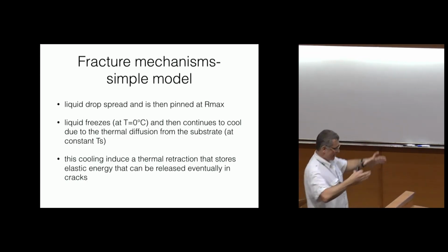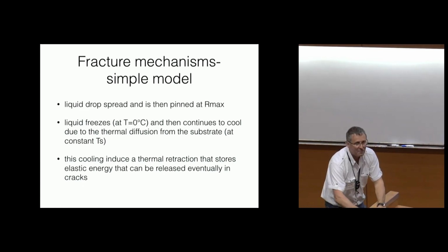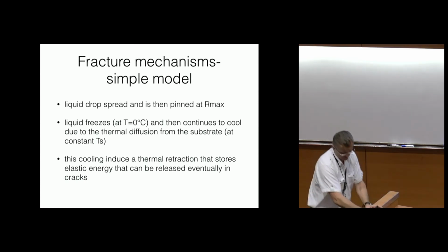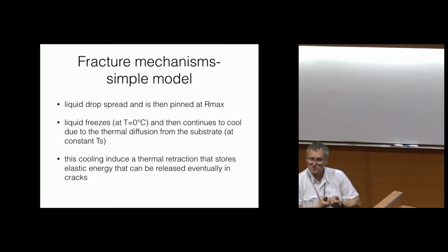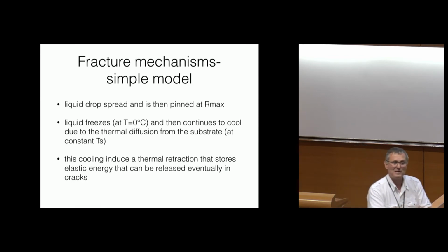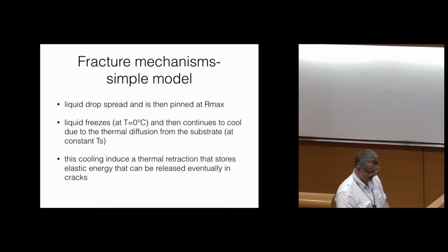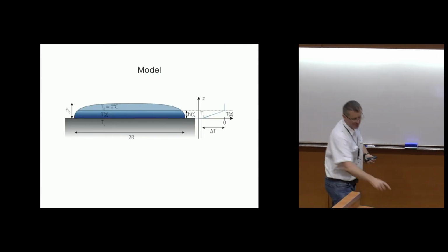But since our drop is stuck on the solid substrate by adhesion, it cannot move. So that means you will create thermal stress or elastic stress in your system. And if the elastic stress is big enough to create cracks, then you will create a crack, preferably to having elastic stress. So this is exactly the classical theory of what we call the Griffiths theory for cracks.